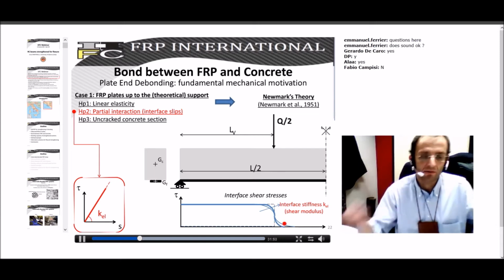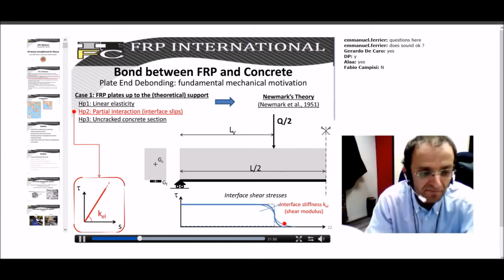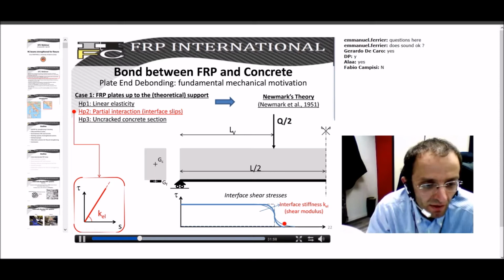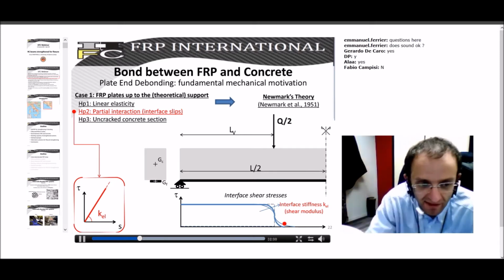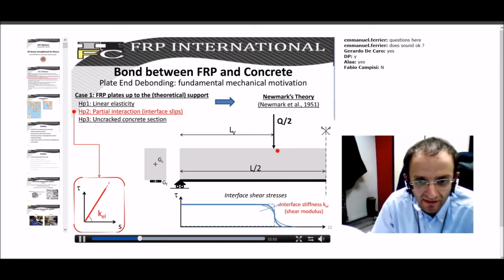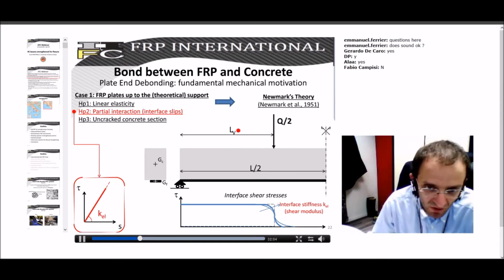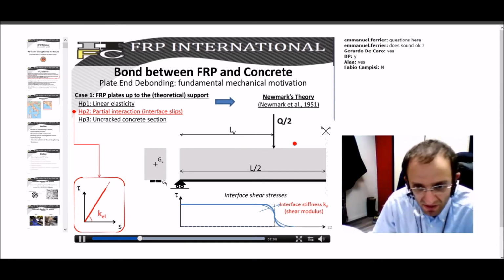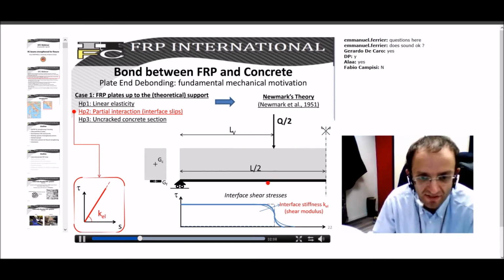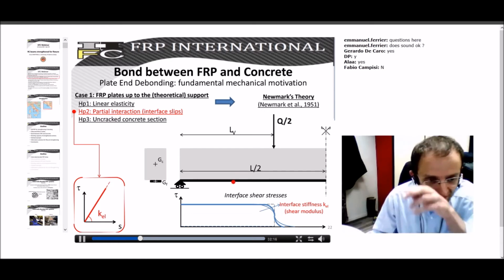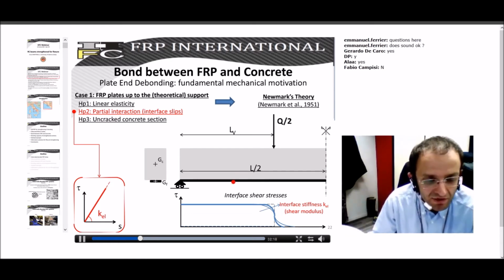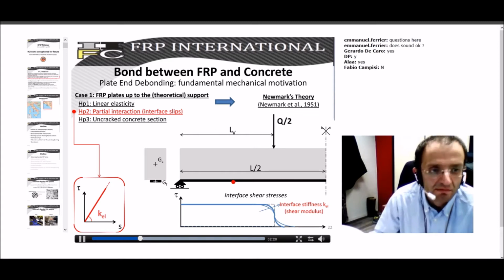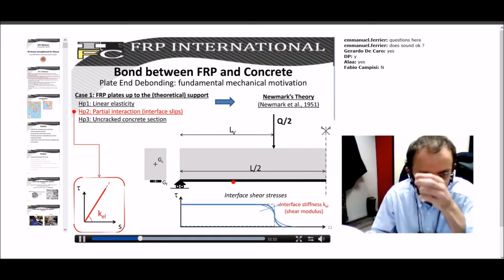So you have this more regular transition between the part in which the shear force is non-zero and the part in which the shear force is actually zero. So we have now a model of a more realistic situation: two materials glued to each other, with some interaction, some partial interaction, some displacements developing at the interface.